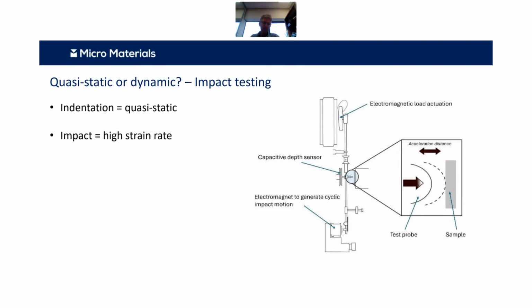So nanoindentation is a so-called quasi-static test technique. In many real-world processes, including biological samples, the impacts involve high strain rate processes. So impact is really more important. So we can generate these impact tests, these high strain rate tests in the nanotest, and there's a schematic of it shown there. We can pull the probe off the surface and fire it in under these to generate these high strain rate indentation tests or impact tests. And if we want to, we can go backwards and forwards and look at cyclic tests.